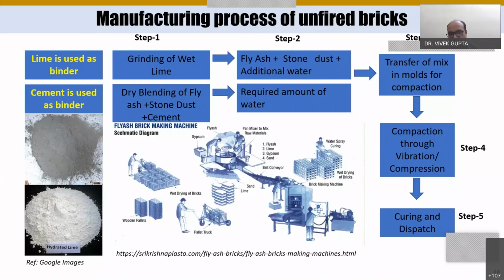So what is our target? Basically, in the drying area, we want to achieve a particular early age strength, so that we can handle them and stack them up to a certain height. And in the final curing, we reach a sufficient strength, so that we can dispatch for utilization. Still, in the case of lime, many researchers have reported that lime and fly ash gain strength up to 1 year. So it's not that we have achieved the complete strength, but the majority of it we have achieved before the dispatch of the material.